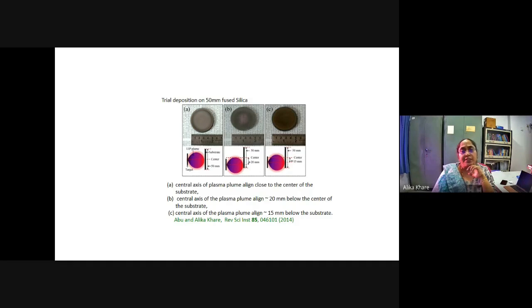So if we make it off-axis, in the second case, it is two off-axis. In this case, what happened is that in the center there was hardly any deposition. One can see a sort of donut kind of deposition has taken place, and with careful enlargement, one can read whatever is printed at the center of it.